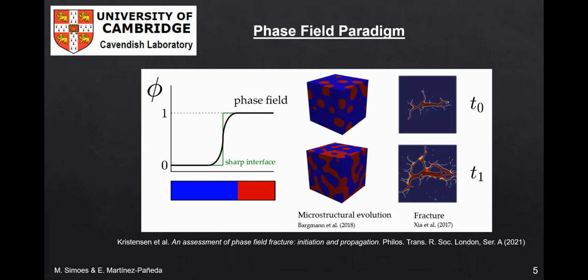So for example, in the case of fracture applications, the phase field can take a value of 1 in the cracked phase and of 0 in the undamaged material points, varying smoothly in between. The temporal evolution of the phase field variable is then described by a differential equation that can be easily solved using standard numerical methods, making the tracking of evolving interfaces computationally tractable.